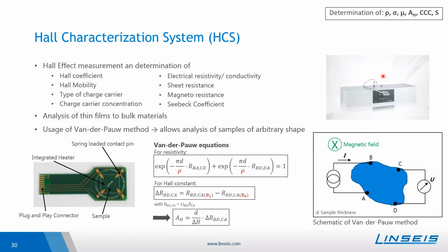The difference to the HCS is that there are also different magnet options available, so that the Hall coefficient can also be determined, using here the Van der Pauw equations. In the end we get the Hall coefficient, the Hall mobility, and the type of the charge carrier, indicated by the plus or minus sign of the Hall coefficient. Then we can find out the charge carrier concentration as well. Sheet resistance can be determined, as well as the magnetoresistance.